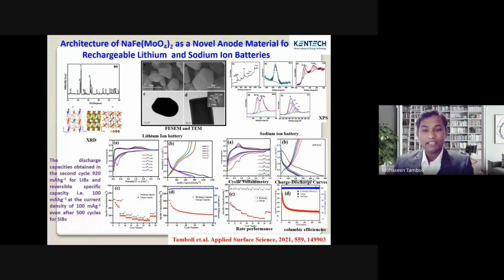We found that it has a cuboidal-like structure, with a size of 1 to 2 micron. We also studied the XPS of this electrode, and we found that all the elements of sodium iron molybdate, such as sodium, iron, molybdenum, and oxygen, are present here. The oxidation state is crucial for the development of this novel material. The oxidation states are: sodium is plus 1, iron is plus 3, molybdenum is plus 6, and oxygen is minus 2, respectively. This is a crucial part when we develop a novel electrode material for any application.